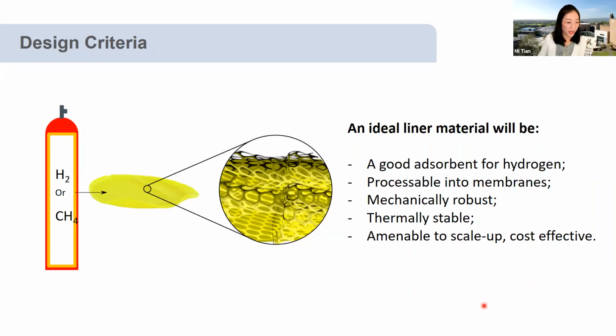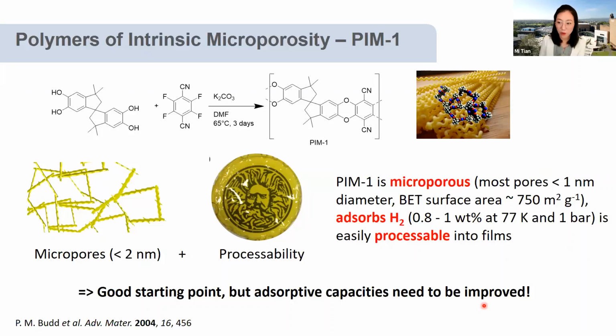So we want to find a material that can be processed into a membrane, and it also needs to be strong enough to sustain high pressure, be thermally stable, and be able to scale up. Then we found the polymer of intrinsic microporosity, PIM-1, a porous polymer. Polymer is a kind of plastic, we can think of it that way. This polymer was invented about 15 years ago by Neil McKeown at UEA, and this material is very interesting. It can be processed into this yellow and transparent membrane, and it has microporosity, and the pore size is less than 1 nanometer.